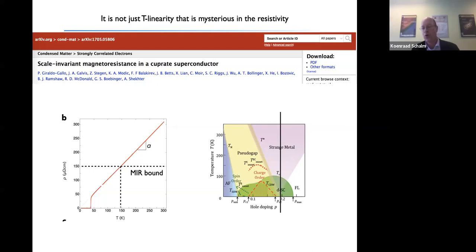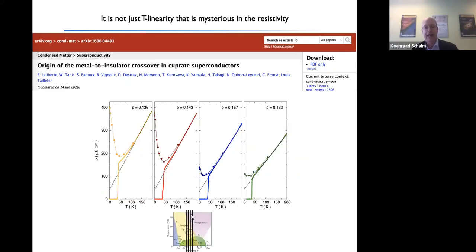Every time you go through a phase transition, or even a smaller type of transition in the metal, you expect the scaling of the resistivity with temperature to change, right? The simplest example is, of course, when you go into the superconducting regime. You see that the resistivity changes, it becomes zero. And likewise, if you take slices at different stages, you would expect that every time you go from the pseudogap phase to the strange metal phase, or whatever other transition there is, you would see a change in the resistivity at those values of the temperature. This does not happen. Somehow or other, this linear in T resistivity is super robust.